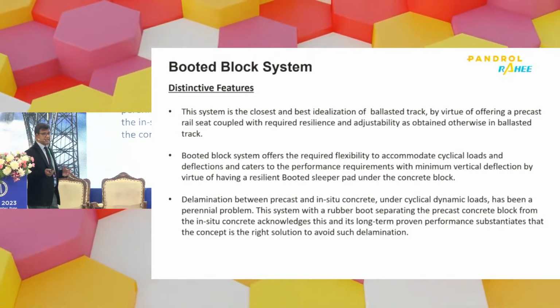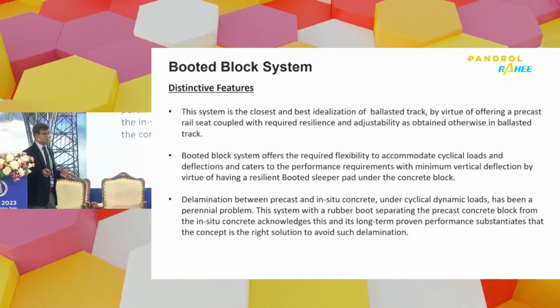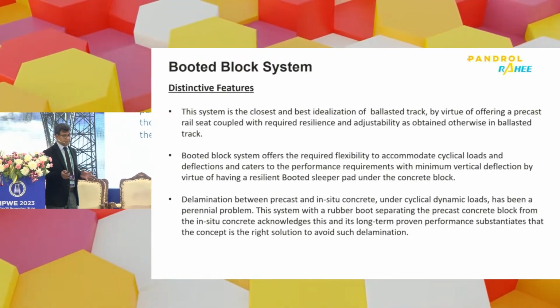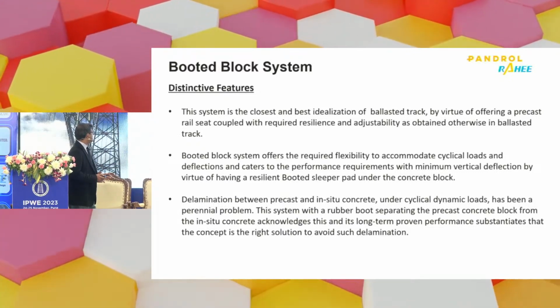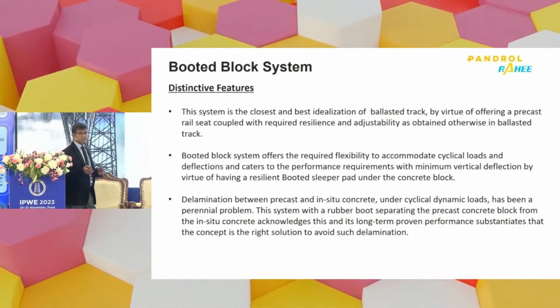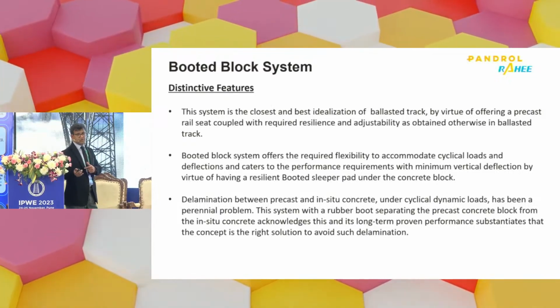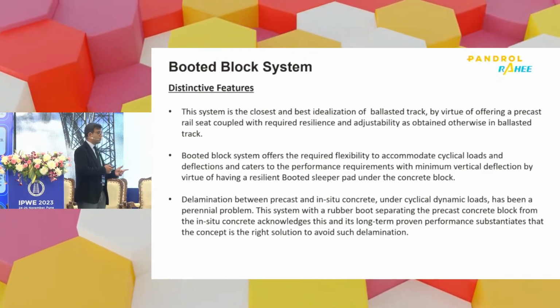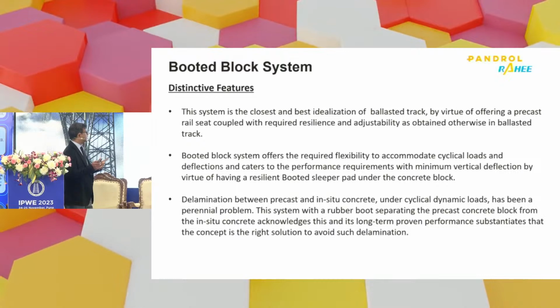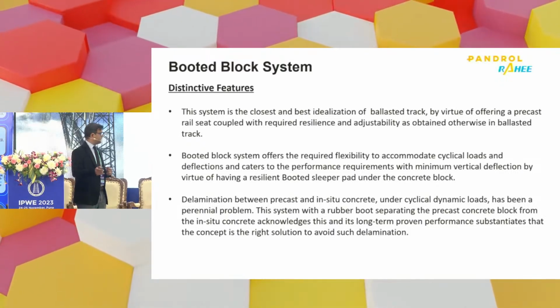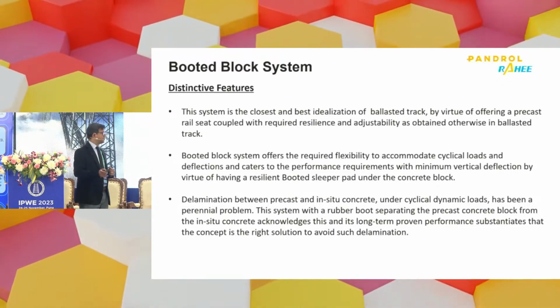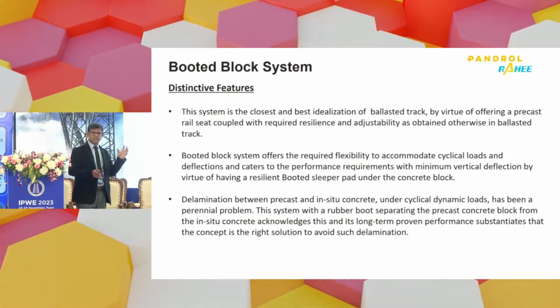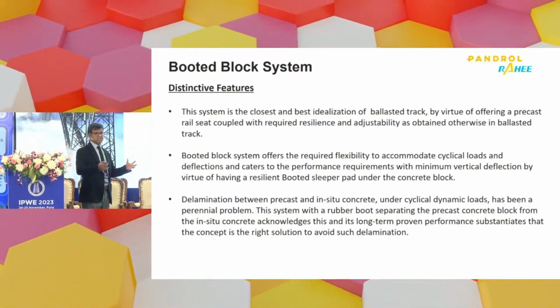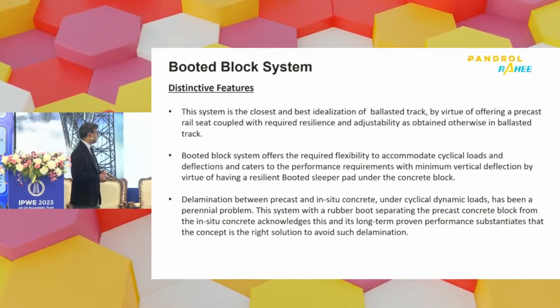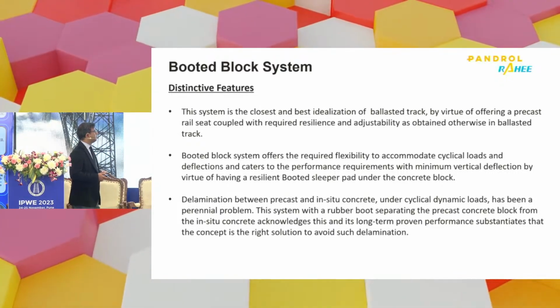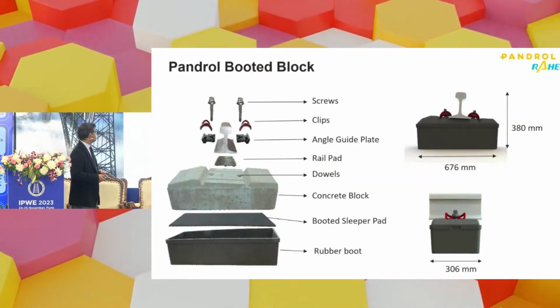Delamination between precast and in-situ concrete under cyclical dynamic loads has been a perennial problem. We have seen multiple failures on that front. This system, with a rubber boot separating the precast concrete block from the in-situ concrete, acknowledges this, and its long-term proven performance substantiates that the concept is the right solution to avoid such delamination between the precast and the cast in-situ concrete if they are juxtaposed against each other without any rubber layer in between. So here, the rubber boot provides that benefit.